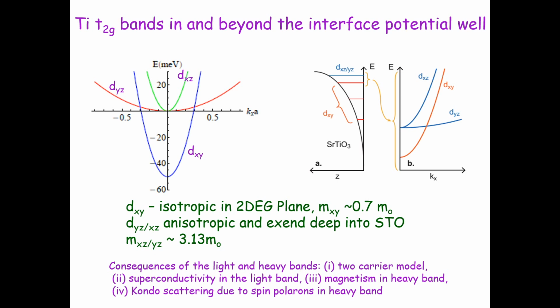Sorry, why would the low mass band have low mobility and the high mass band have high mobility? Yeah, that is a little contradiction there. It turns out that these two bands can extend deep into strontium titanate, and they take there the advantage of high dielectric constant of strontium titanate.